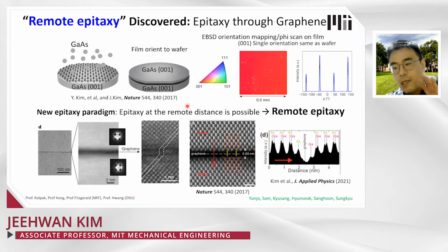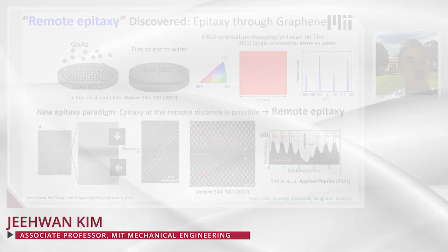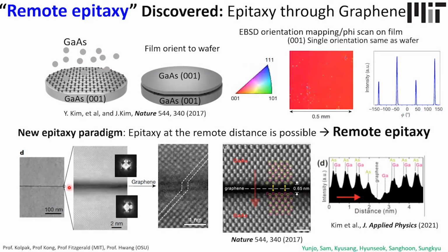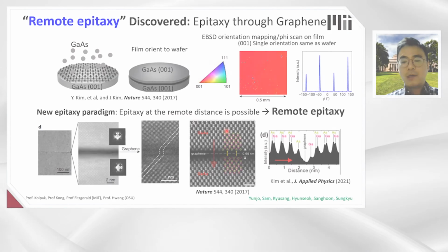Please have a look at these quite crazy TEM figures here. We found that even if there's graphene between the epitaxial layer and the substrate, this epitaxial layer still follows the crystalline information of the substrate at a remote distance. So we name this scientific phenomenon remote epitaxy. Okay, so that's what we have found.